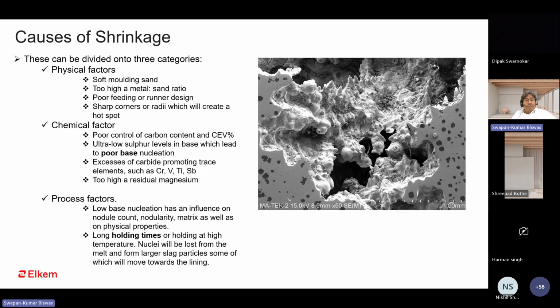Also, another parameter is the residual magnesium. Most of the time, foundrymen think that if residual magnesium is on the higher side, then there will be no compacted graphite. That is correct. But on the other side, it will increase the shrinkage tendency, because magnesium is a very strong carbide promoter. When your residual magnesium is on the higher side, there is always a tendency for carbide formation, and you will get a lower nodule count. When nodule count is on the lower side, then your shrinkage tendency will increase.